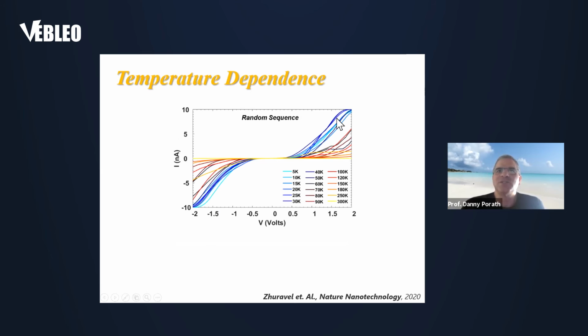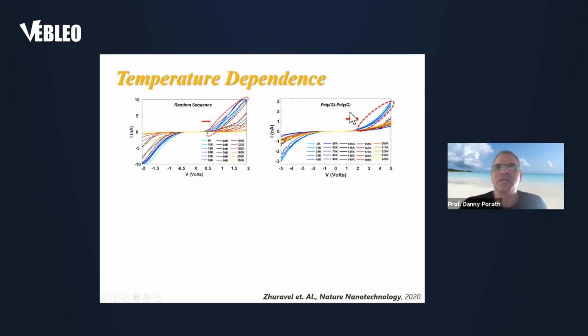So you can see that the colors are representing the temperature, starting from 5K and up to room temperature. And you can see that at lower temperatures, up to 50K, there isn't much change in the current. And then after 50K, there is a start of a decrease of the current to lower currents, usually at room temperature. And similar behavior was also observed for the homogeneous poly-G, poly-C DNA.